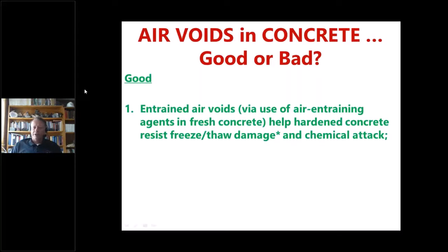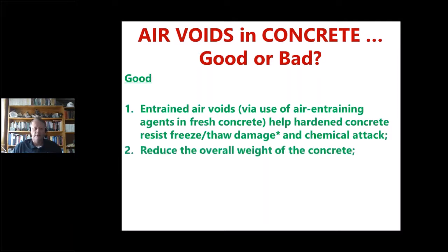So are air voids in concrete good or bad? Well, the air voids in concrete present a double-edged sword, essentially. The good aspects of the air voids, I'll list them here. Number 1, especially with the entrained air voids, they help the concrete resist freeze-thaw damage. That's the big reason behind entraining your concrete with air, so that it can resist freeze-thaw damage and chemical attack. But freeze-thaw damage is the big one. I'll elaborate on that in a second.